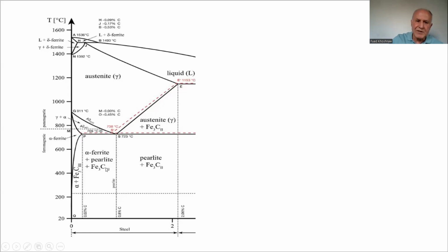What do we have in steel? We have ferrite and pearlite. And these are two different, ferrite and cementite to make pearlite. So pearlite is the combination of ferrite and cementite. These are two different chemical compositions. And this by itself is a galvanic corrosion because of two different compositions, two different microstructures, ferrite with cementite. So when we go to the grains, this is already not a solid solution, so not a homogeneous microstructure.